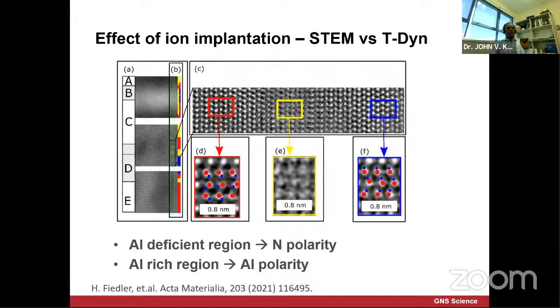So this is really a high quality STEM image to probe the defects and the regions where it changes the lattice, and also the defects occur in different parts of the lattices as well. In those days we simply did normal TEM, but these days you have this kind of STEM image with annular dark field, which precisely gives you each atomic layer, so you can look at where the real defects are happening. This is great because it is a high resolution way of understanding the defect layer information from the crystal films. So we looked at it very closely.